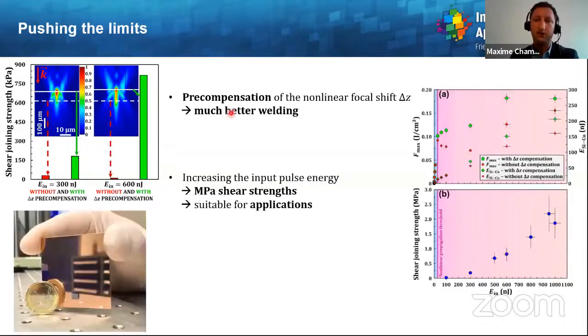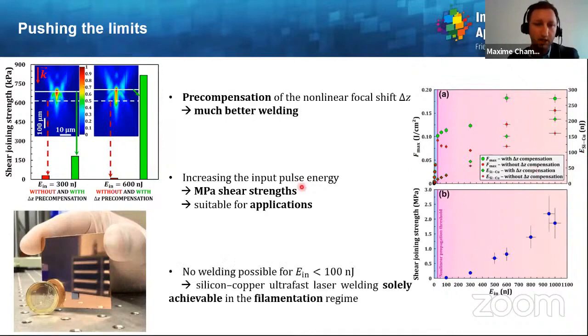And the results are essentially shown here in the bottom. So the shear joining strength as a function of the input pulse energy, and you can see that around 1 microjoule input pulse energy, one can reach around 2.2 megapascal shear joining strength, which is quite suitable for applications. And the reason is that when you precompensate the nonlinear focal shift, you increase the maximum fluence at the interface, as well as the energy deposited at this interface. I mean, the energy reaching the interface, sorry.